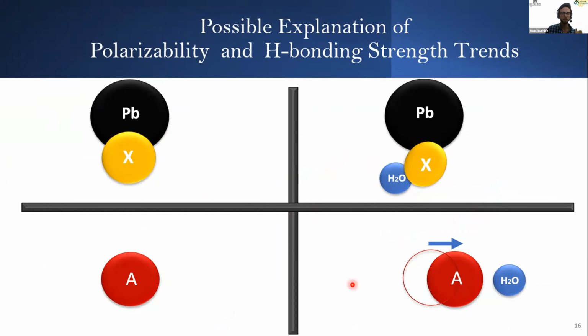For the A-site cation, the hydrogen bonding between the A-site cation and the water molecule would draw the A-site cation out of its ideal position for mechanical integrity, thus weakening it. So the stronger the interaction, the more the integrity of the structure is weakened. So it's easier to break, which we measure as a lower hardness.